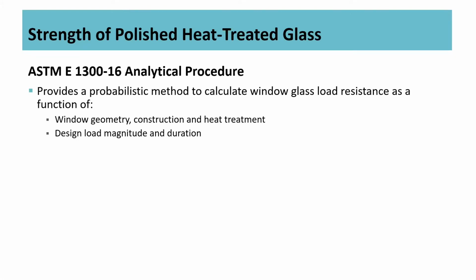And so in the US, we've been using ASTM E1300 to specify glass thickness for windows in buildings. And recently, we've added a new analytical procedure to the standard that's going to allow us to assess some of these changes that we're doing to the glass, namely that we're reducing the thickness in localized areas, and correspondingly, we're likely reducing the heat treatment layer that is at the surface of the glass as well. And so we want to make sure that we can calculate and show that the glass still has the appropriate capacity to stay on the building.